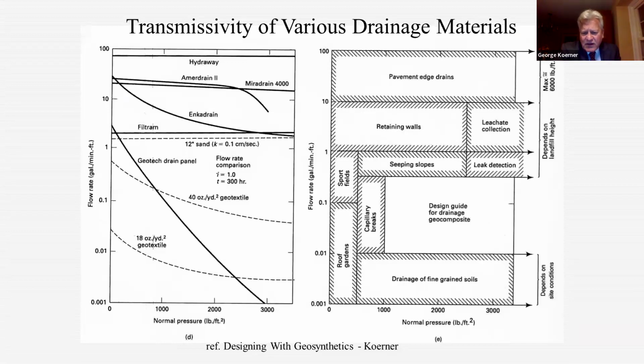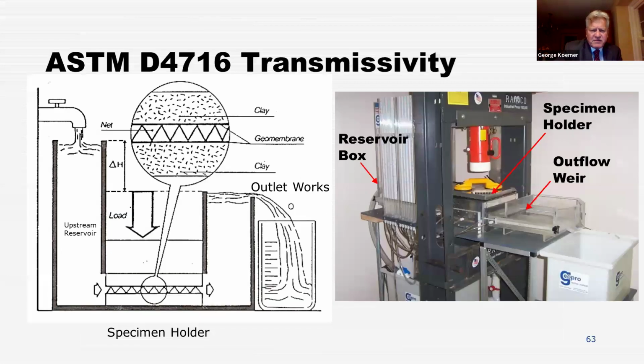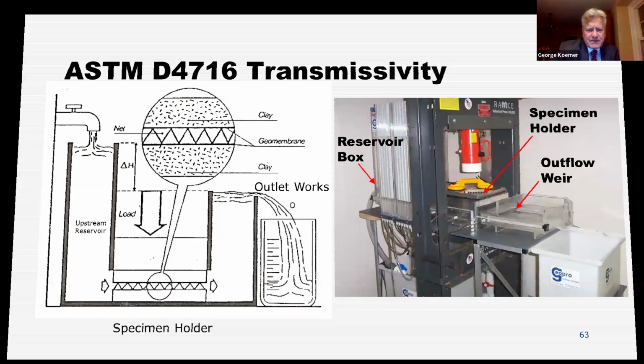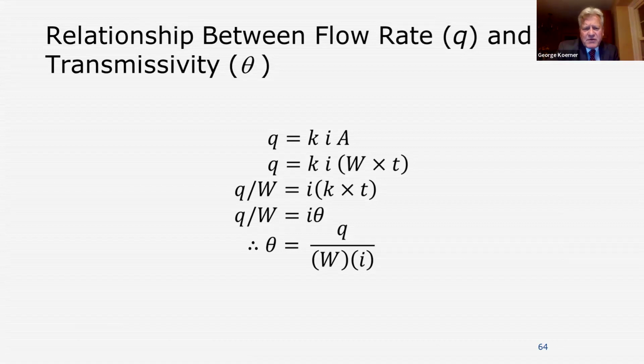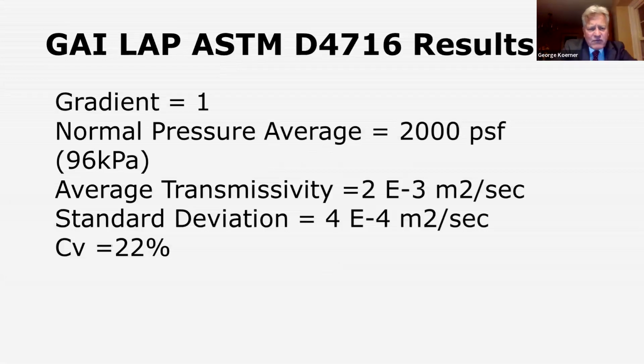You see the retaining wall up there, and you're looking for a transmissivity value or a flow rate value at a normal pressure. We're targeting around 2000 PSF, and looking for a flow rate. The flow rate comes from a transmissivity unit. You see it here in cross section and photo. It's ASTM 4716. The relationship between flow and transmissivity is shown here, and the test results at a gradient of 1, because this was a vertical installation.